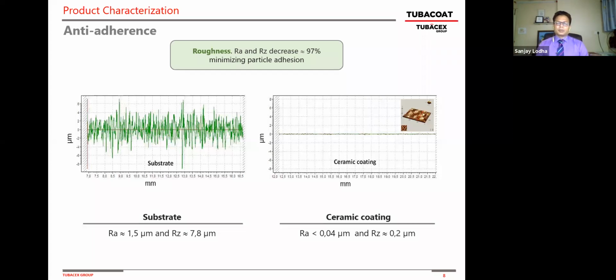Essentially, we bring you the surface of the coated tube that's equivalent to a glass finish, a mirror finish, very smooth. And we know the smoother the surface, there is less resistance to the flow, and less resistance for the particulates and metal compounds to deposit on the surface and begin the fouling process. So by having this smooth surface, we're minimizing any tendency for the particulates or any other matter to deposit and begin the fouling and the corrosion process. Next slide, please.